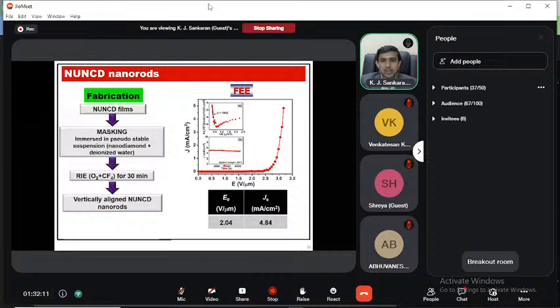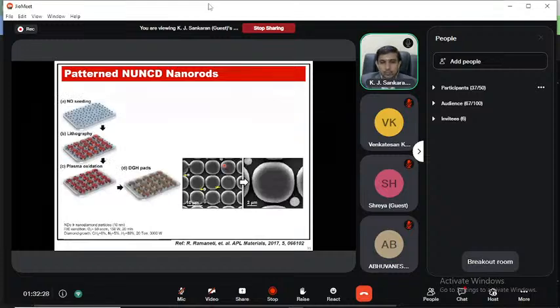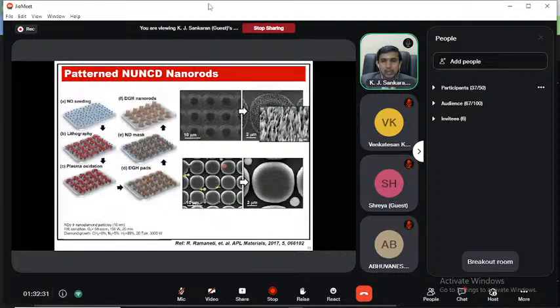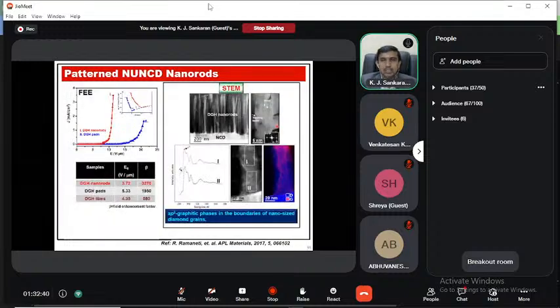Then the field electron emission studies were carried out, which showed a further improvement in the field electron emission, with a low turn-on field, high current density and a better field electron emission pattern. Now we have shown only the NUNCD nanorods, but can we pattern them to improve further? We followed a basic lithography process that creates the NUNCD nanorods in a patterned way, and you can see these are the NUNCD nanorods. The same image shows that each nanorod is a hybrid of graphene and diamond, which makes these hybrid diamond nanorods have a low turn-on field with a high aspect ratio and a high field enhancement factor.